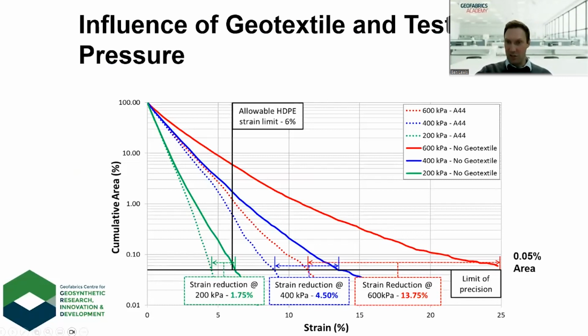So just quickly looking at this chart, the red solid line and the red dotted line. The red solid line represents a 600 kPa compressive load over a rocky subgrade, particular sort of grading of rock with no geotextile, and that induced a strain of 25% on an HDPE. Now, HDPE tends to have a strain limit, or we're trying to limit that localized strain to 6%. Sometimes it's 2%, depending on the engineer.